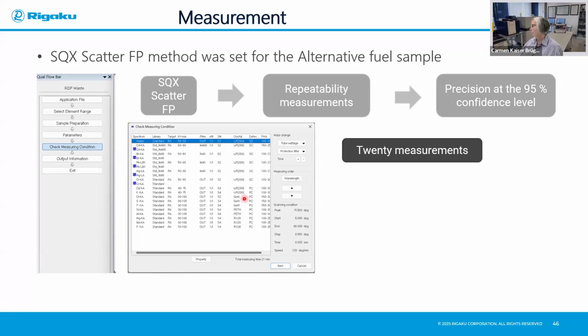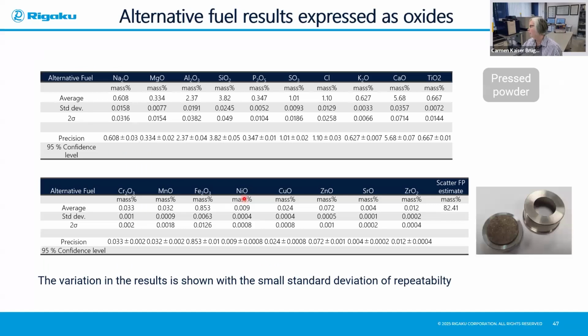As mentioned, we always need to look at the stability of the measurements, so we can do repeatability measurements here. Just to show you how stable an XRF is, it's all about precision, not about accuracy. So the precision of a result can be shown by basically preparing the sample 20 times and measuring the sample 20 times. So here you can see a table where we average the results of the 20 measurements using the scattering FP. For example, we spoke about zinc a lot, so we can look at zinc, and you can see on average we get a value of 0.072% with a very small variation in the repeatability measurements. So this shows that XRF is a very reproducible method and has a very small deviation in the results. Once again, showing the precision of the result.